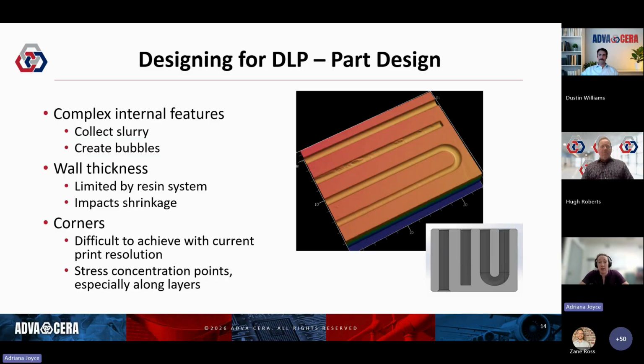So we can make all of these complex internal features, but depending on how they're designed, you get different impacts. So if we look at this part here on the screen, we've got a through channel, a blind channel, and then a U-shape channel. And each of those have different abilities to be cleaned because of the aspect ratio, how long and skinny they are. The blind hole is the least cleanable because while you can blast solvent in there, it doesn't really rinse out. The U-shaped channel has that feature down on the end, but it's a lot easier to clean because we can flow the solvent all the way through.